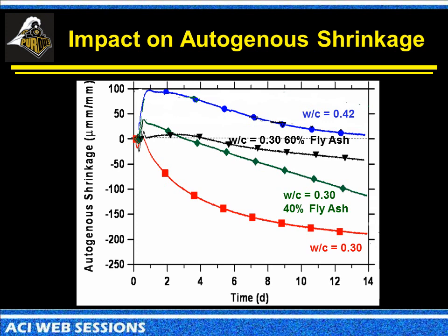But the one thing that I want to point out when we look at these curves, the shape of the curve is very, very important when we're starting to look at autogenous shrinkage. If you see our conventional Portland cement mixtures, we have a substantial autogenous shrinkage that's occurring during the first couple days as we drop the water to cement ratio. That's not necessarily the case when we see these fly ash mixes, but when you look at the slope of this line, it continues out. And we've continued these tests out to 28, 90 days, and at about 21 days, these two lines will start to interact with each other.